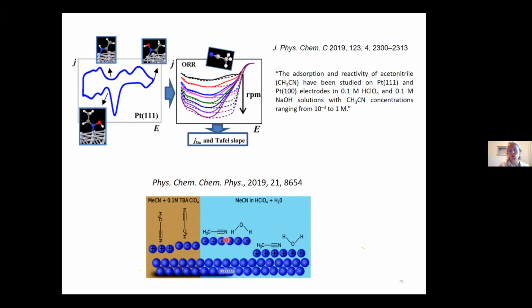And actually the orientation of the acetonitrile is also being dictated by the mole fraction of the acetonitrile versus the water. And we think of similar things going on, that the acetonitrile in some way is habit modifying the palladium crystals that we're growing. It's slowing down the growth, whereas in water, it seems to be growing in this three-dimensional structure and going dendritic. But as I said, it's interesting to us.